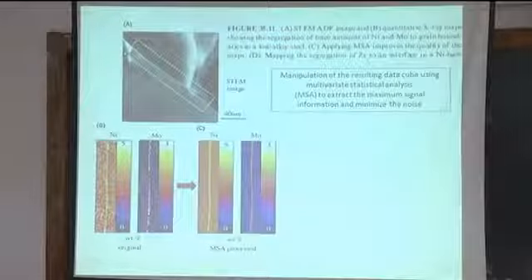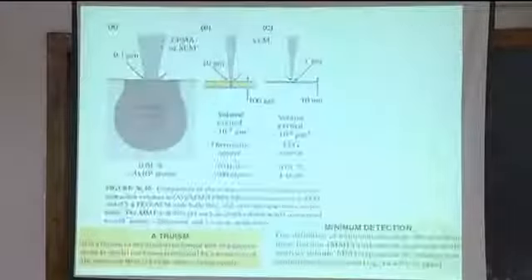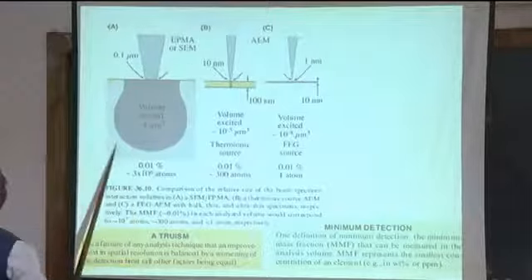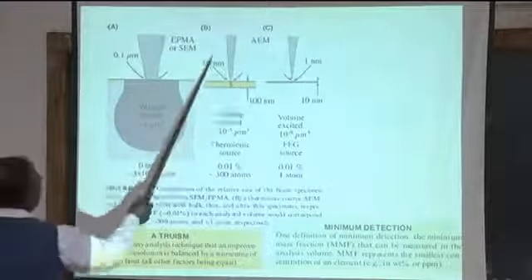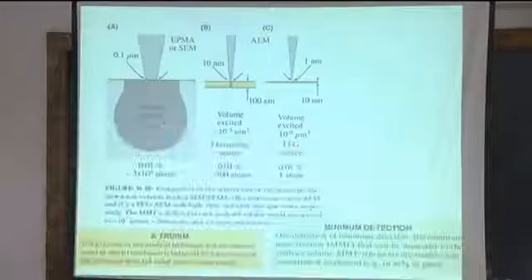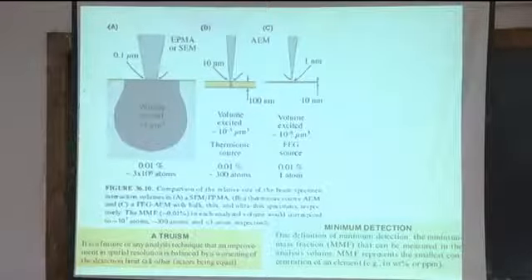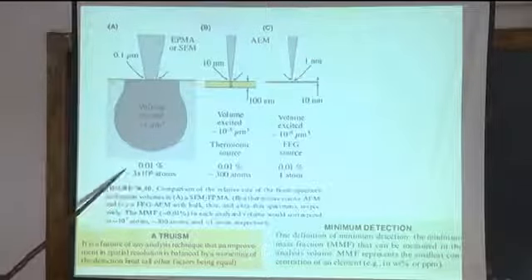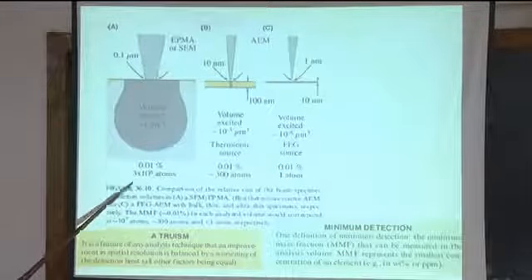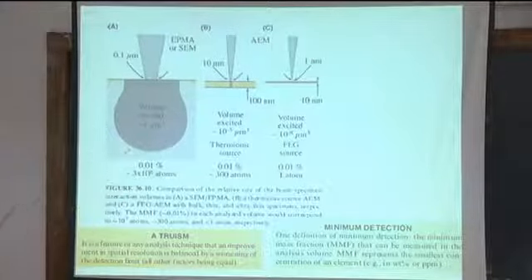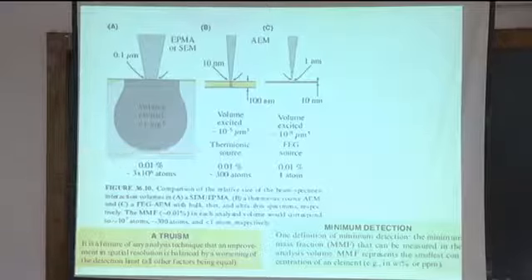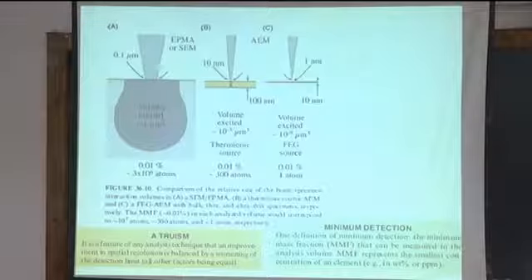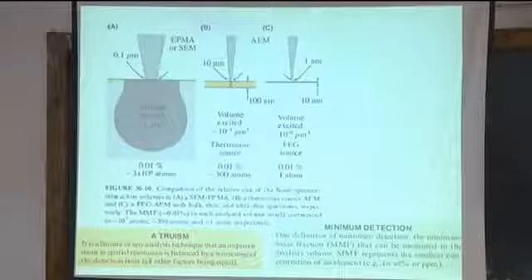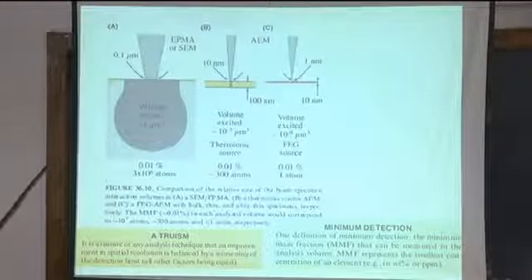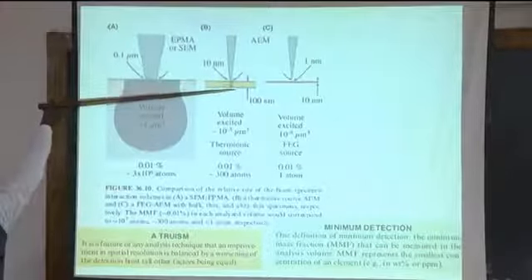Now, this is another grain boundary segregation, STEM. I'll go to this. The advantage of doing it in an EPMA or SEM versus in a TEM is shown here. You see interaction volume is very large in EPMA or SEM. So when you are analyzing, the number of atoms giving your signal out is this many. And that is how it is a bulk analysis, although it qualifies as a surface because it is still 1 micrometer. If you take any material, 1 micrometer is very, very small. But in the context of XPS, AES, this is at least 100 times or so thicker. Now in the TEM, you make the sample very, very thin. That is the thickness. You can make it still thinner.